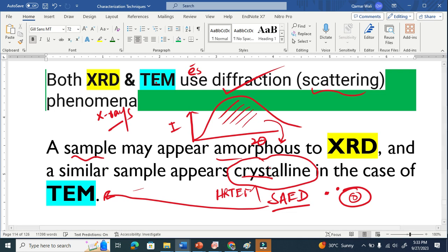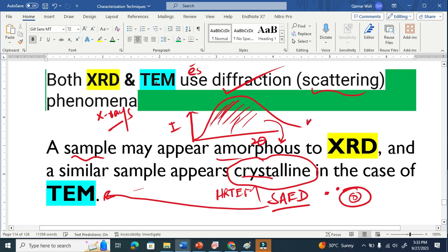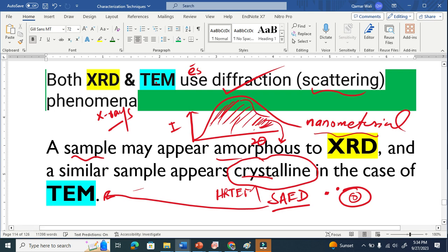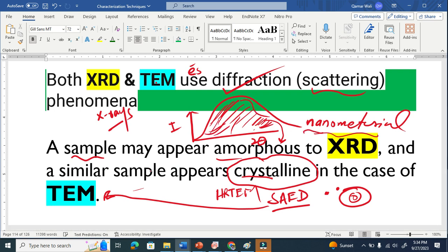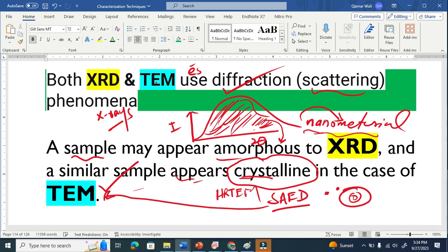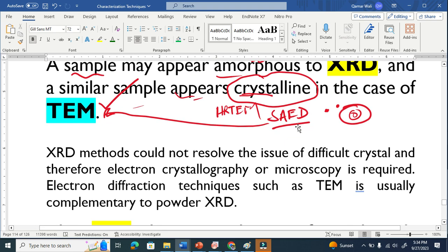So where is the problem? The problem is that we also get this broad peak from nanomaterials. In XRD, amorphous material and nanomaterial give exactly the same broad peak shape. So from XRD alone we cannot determine whether the material is amorphous or a nanomaterial. But once we perform TEM, we clarify that the material was actually crystalline — the broad peak was simply due to the nanoscale size. This is why we need to compare these two techniques.